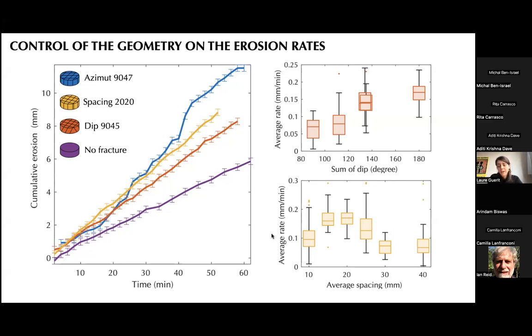At the bottom here, I've focused on the experiments with various spacing. So again, it's the average erosion rate, and this time with respect to the average spacing of the fractures, because we use a squared network, but we also printed some rectangles. So it's the average of the two. And we observe this very nice curve, which suggests that there is an optimal spacing for plucking for erosion to occur. And I will go back to this idea in a couple of slides.